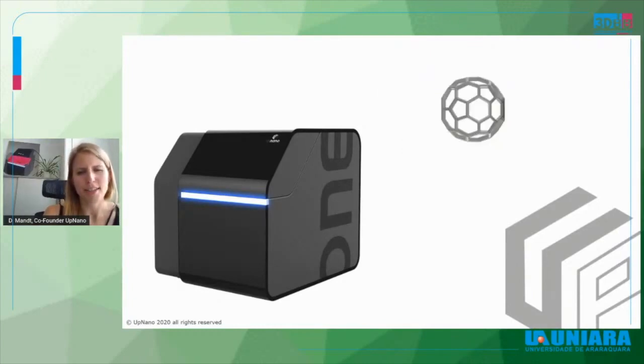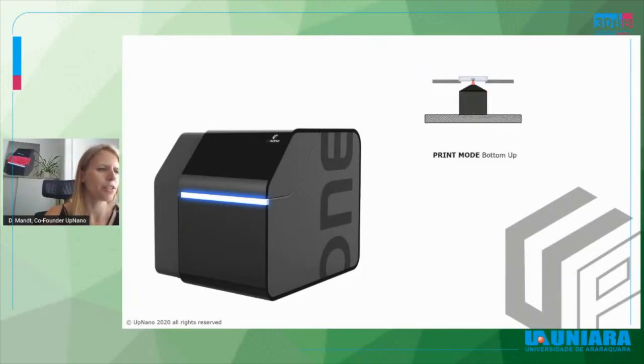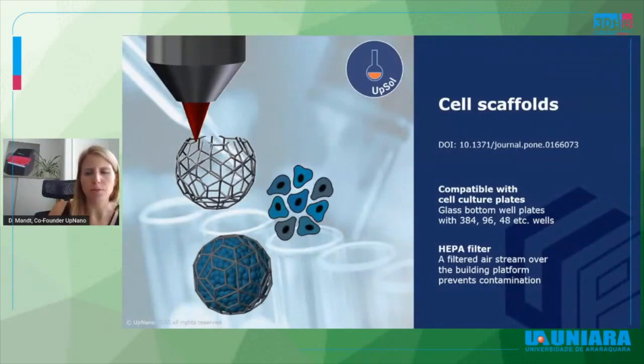Here again, you can see one of these cages being printed. Here you can print an array of cages at the same time. So the maximum we are printing now is above 300 of these scaffolds on the 20 by 20 substrates. Or you can, for example, use a 96 well plate and place one of these cages in each individual well. So there is a software interface where you can put the STL files basically in the individual wells. And also the parameters of these printed objects, so of the cages in that case, can be varied from well to well.